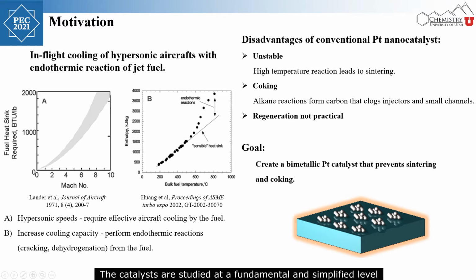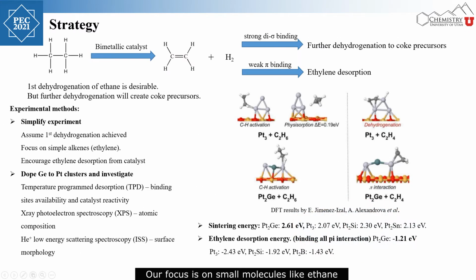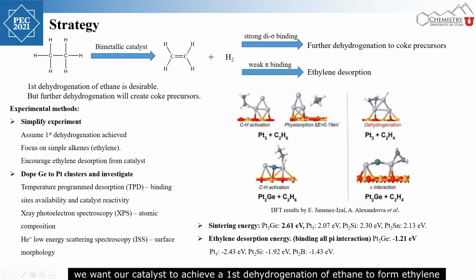The catalysts are studied at a fundamental and simplified level, where we use flat alumina supports to hold bimetallic clusters in an ultra-high vacuum environment. Our focus is on small molecules like ethane. For endothermic cooling purposes, we want our catalyst to achieve a first dehydrogenation of ethane to form ethylene.